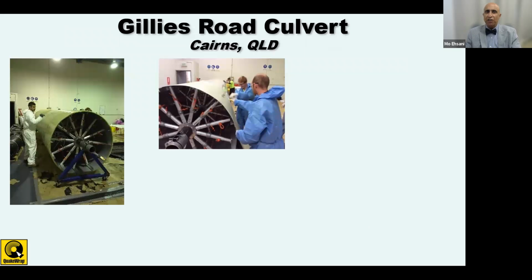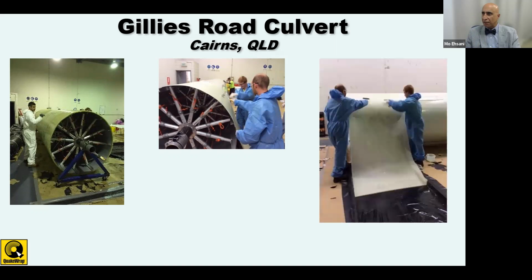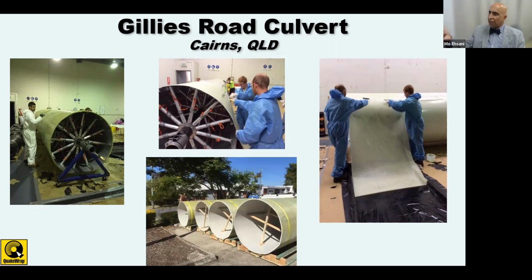One application of this product is to make a pipe that we call stiff pipe. This is fairly easy to construct. You make a mandrel like you see here. The mandrel has telescopic arms that you can pull in and out to create the diameter that you want. We'll put on the skin of it a sheet metal typically, and then the layers of fabric, and that 3D fabric and so on are wrapped around that mandrel, and they cure at ambient temperature overnight. So the next day, you collapse the mandrel, pull the finished pipe out of the mandrel, and repeat that process.